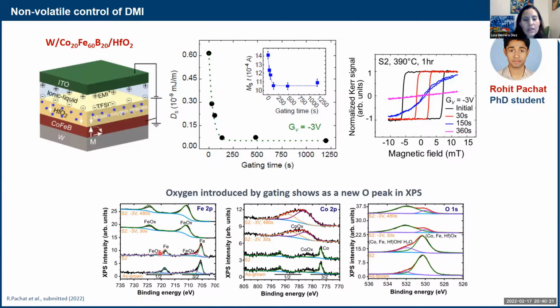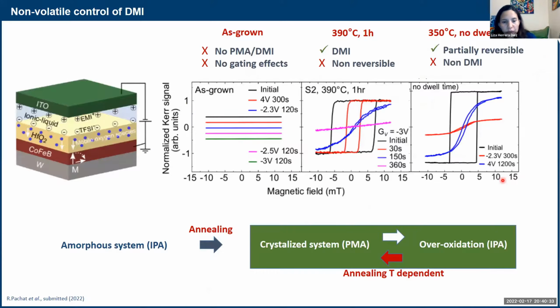There we can see very well the evidence for the oxidation of iron, the oxidation of cobalt, and the appearance of this peak of the mobile oxygen. What is interesting from here is that in this system, especially without a top interface with MgO, which is ideal for PMA, in the as-grown state, we couldn't see anything. There was no PMA, there was no DMI, and no gating effects. So here we can see very well that although we are putting oxygen inside, that oxygen is not the key aspect that is going to give us PMA like in the other systems.